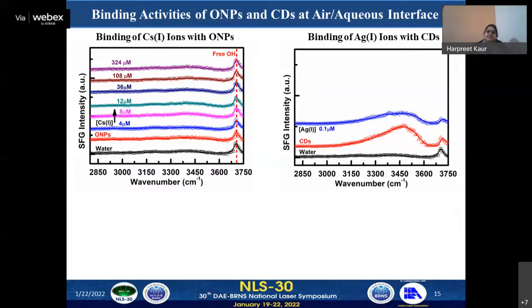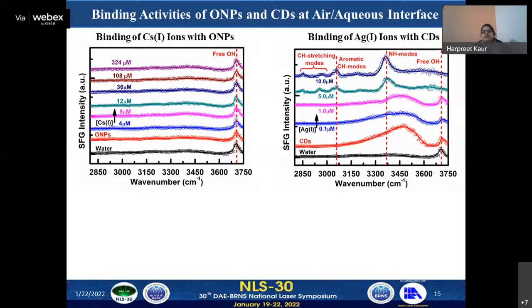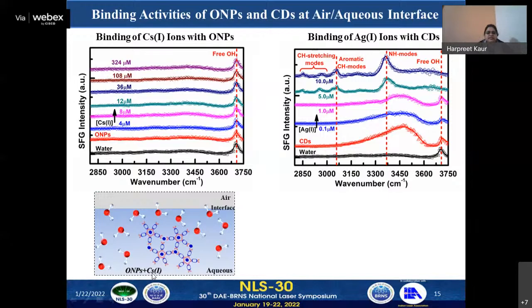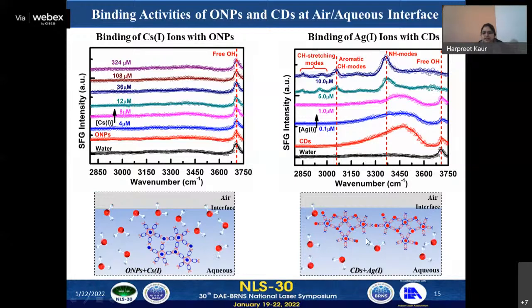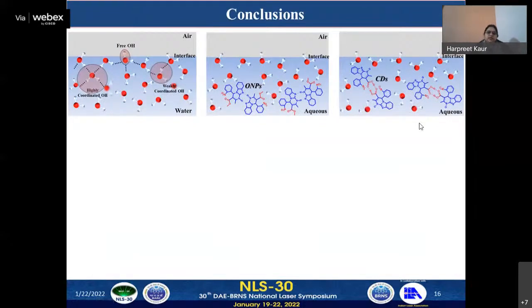And on addition of the silver ion to this system, we have found this overall intensity enhancement is suppressed, and further increase has shown the appearance of CH and NH stretching modes with complete elimination of free OH at the interface. So from these studies, we have found that the organic nanoparticles, while binding with the cesium ion, prefer to stay in bulk, whereas carbon dots show surface coverage while binding with the silver ion. So organic nanoparticles have no impact on the interfacial water structure, whereas carbon dots have shown the ordering of the interfacial water molecules.